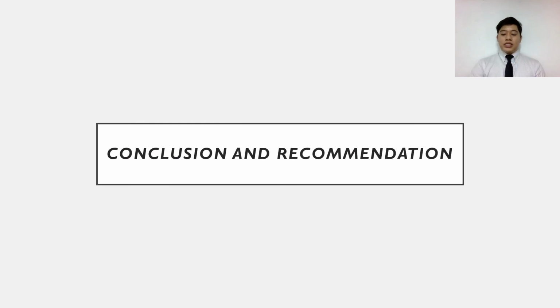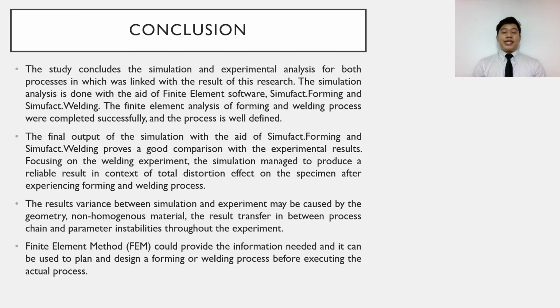For conclusion and recommendation, to conclude the study, the simulation and experimental analysis for both processes were linked with the results of this research. The simulation analysis is done with the aid of finite element software, Simufact Forming and Simufact Welding. The finite element analysis of the forming and welding processes was completed successfully, and the process is well defined. The final output of the simulation with Simufact Forming and Simufact Welding proves a good comparison with the experimental results. Focusing on the welding experiment, the simulation managed to produce a reliable result in the context of the total distortion effect of the specimen after experiencing the forming and welding processes.